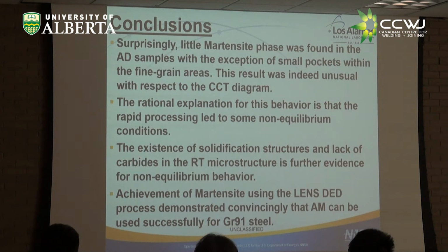There's an epilogue to this too, I'll come back to in a moment. The existence of this solidification structure, which is clear and unambiguous, and the lack of oodles of carbides in the room temperature microstructure is further evidence for what happened there. We must somehow skip that austenite phase field. But we can achieve martensite if we do the normalizing and tempering, and that in and of itself was very useful to do, even if you just take advantage of the advantages of additive by itself.